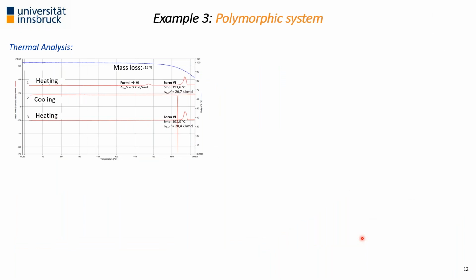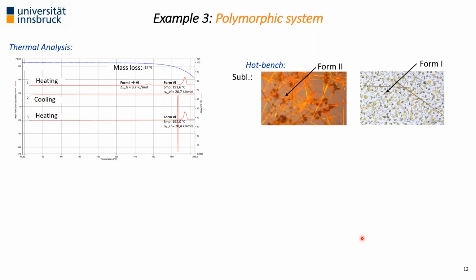So I'm quickly jumping to another application. The next system we have chosen is a polymorphic system. And we already learned that we can produce different polymorphic forms by controlling the temperature or the temperature gradient between the temperature where we keep our compound and the temperature to which we sublime it. In the case of this compound, at lower temperatures, we manage to produce the so-called form 2, long needles. At higher temperatures, we produce more of these block-shaped crystals, form 1. We were interested in whether we could reproduce those experiments in the crystal breeder, but what I should also mention is that those are pretty short experiments. As soon as we sublime for a longer time, we mainly produce form 1.